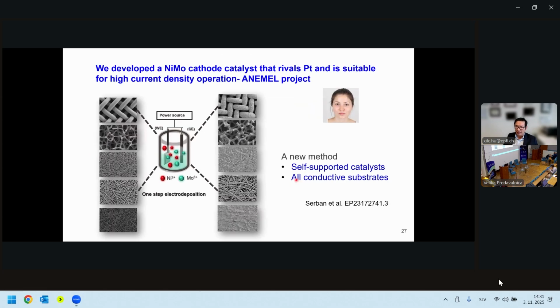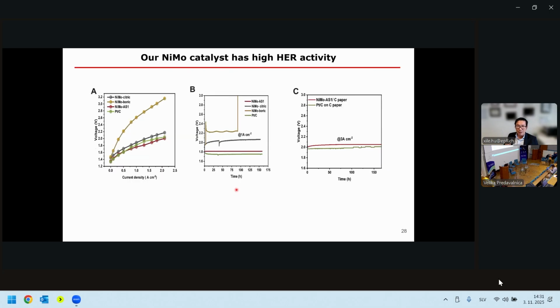Now look at the cathode catalyst, and this is one of the works in our ANEMEL project, where we developed a nickel molybdenum catalyst that is comparable to platinum for high current density operation in AEM water electrolysis. Ariana did this work. She developed these new particles that can make self-supported catalysts on a lot of different conductive substrates. Here I show you some activity plots. There are different kinds of previous nickel molybdenum catalysts, and the one that Ariana has is this color. It's AS1, Ariana Serban 1, and you can see from linear sweep voltammetry that the activity is already comparable to platinum on carbon.